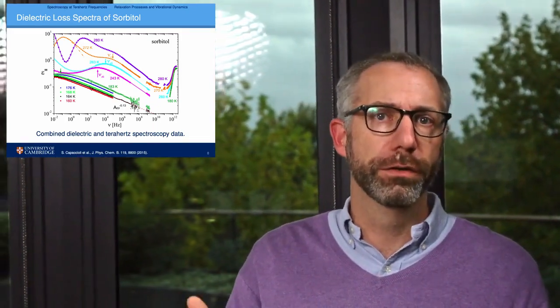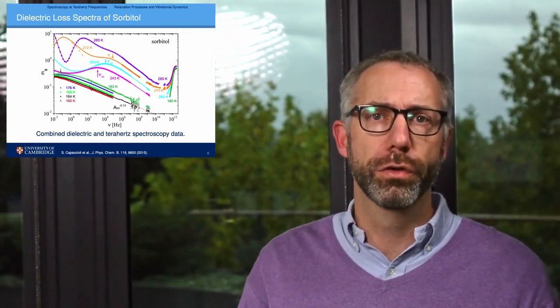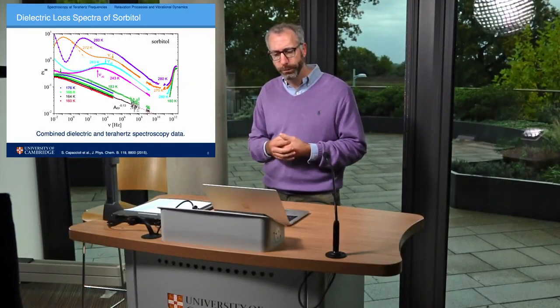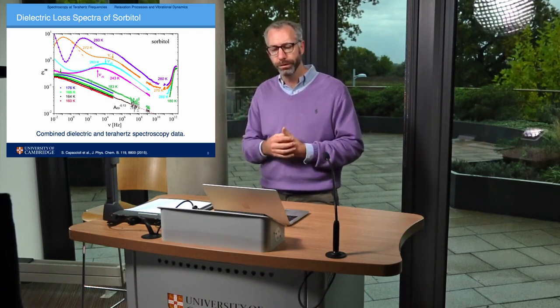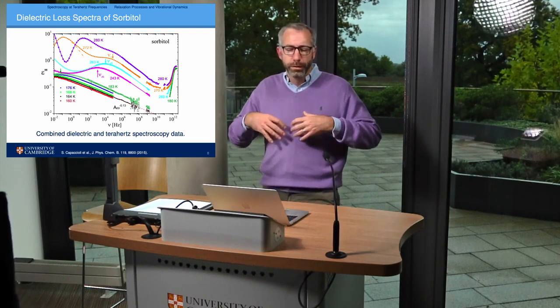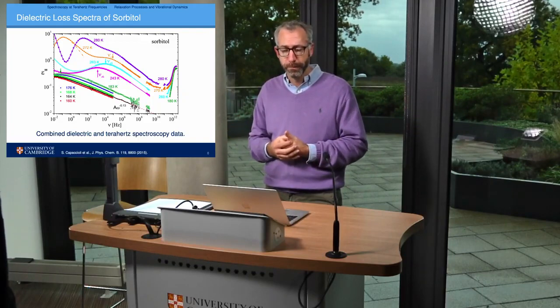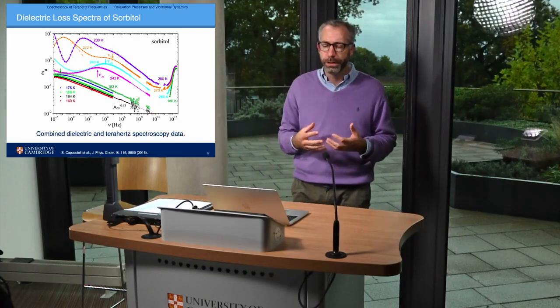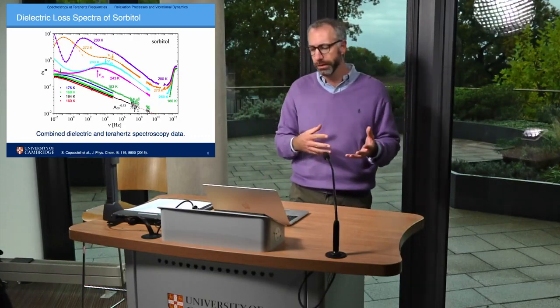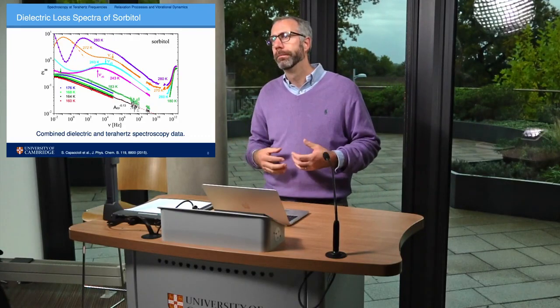That's, for example, described by the empirical law of Vogel, Fulcher, and Tammann. In contrast, at terahertz frequencies, we capture vibrational dynamics of these large amplitude motions that are characteristic for weakly bonded molecular materials. And in solids, the timescales of these vibrations at terahertz frequencies are largely independent of whether or not the entire molecules are translating or rotating at the microscopic scale.